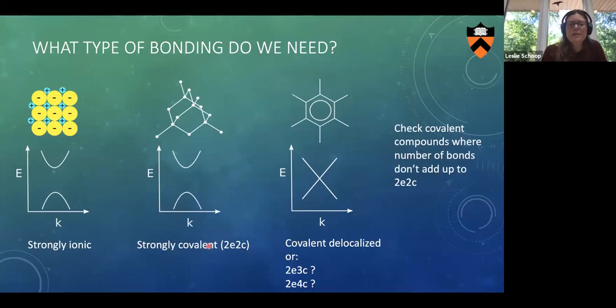And thinking about strongly covalent bonds and what they mean actually resulted in an idea, because these bonds are often referred to as two electron two center bonds, which I put as 2E2C here, which means this chemical bond has two electrons connecting these two atoms, but they do not delocalize like in graphene over the whole system. But in graphene, I have a different type of chemical bond, which does not resemble a two electron two center bond. Only these sigma bonds, like these sp2 bonds, are typical two electron two center bonds, but not the pi bond here.